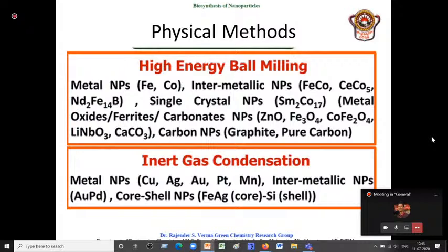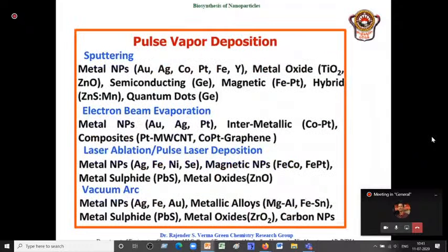Then on the other hand, with inert gas condensation, we can prepare metal nanoparticles like copper, silver, gold, platinum, and alloys or intermetallic nanoparticles or core shell nanoparticles. These can be prepared using this inert gas condensation. Then we have the other methods like sputtering, electron beam evaporation, laser ablation, and pulsed laser deposition. We have a vacuum arc. See these technologies that are available.